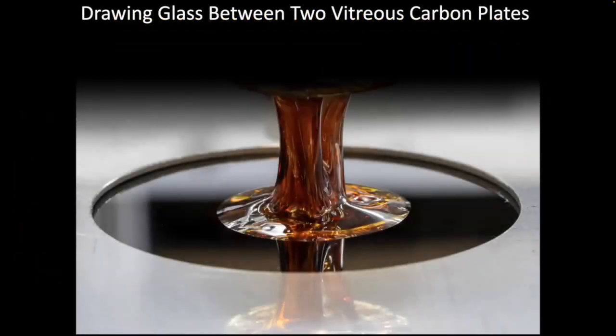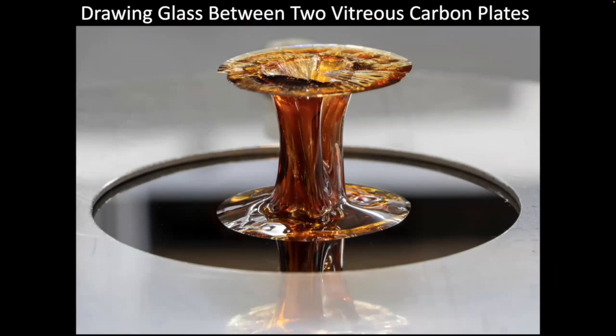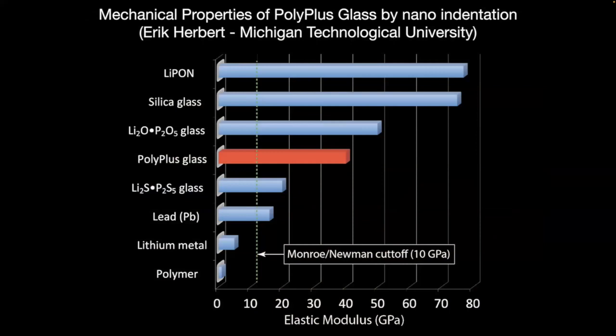You can also see the formability of these sulfide glasses in this photograph, where we put a disc of glass between two vitreous carbon plates, softened it, and just drew it up into effectively a tube. But you obviously cannot do this type of thing with a ceramic material. The melt temperatures would be outrageously high in any case, and they certainly wouldn't draw like this. So this is a unique attribute of these sulfide glasses, that we can process them almost as if they were polymers.